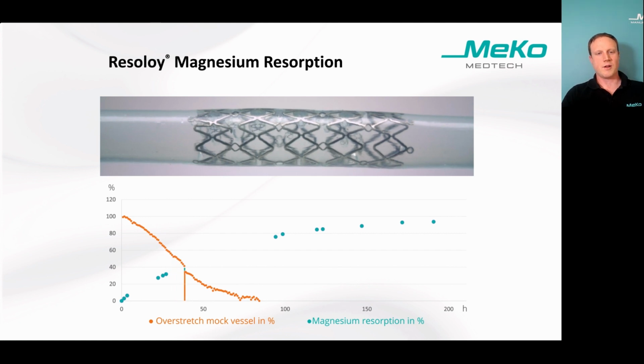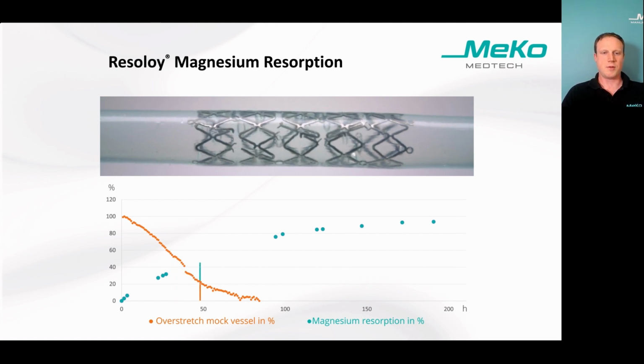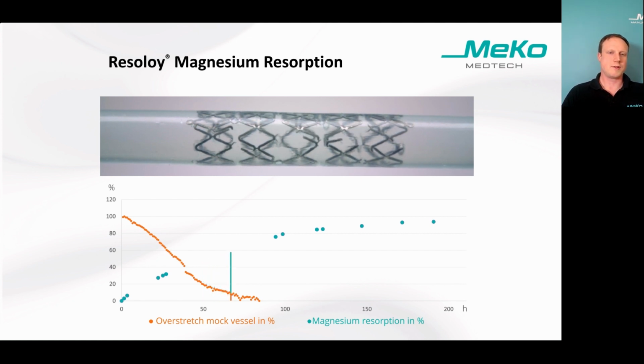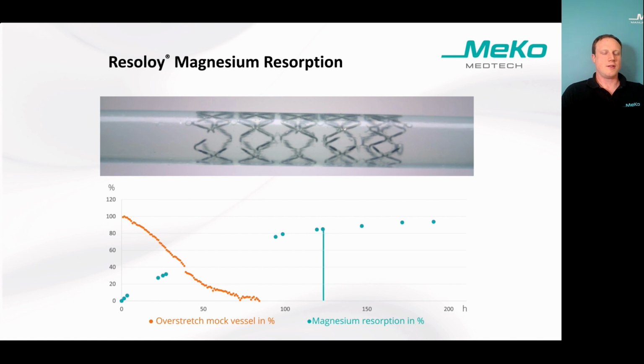On the upper side, you see the implanted scaffold, and the fluid is flowing from the left to the right in this mock vessel. And in the lower part, you see two curves. One curve in blue is the magnesium resorption in percent, and in orange the overstretch of the mock vessel in percent. And as time goes by, you will see the reduction of radial force and the increase of magnesium resorption.